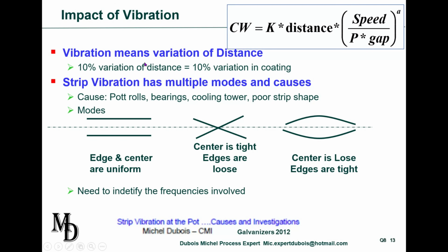Because vibration means variation of nozzle to strip distance. You immediately see that because they are proportional, a 10% variation of distance gives you a 10% variation of coating weight. When the distance is only 10 millimeters, a variation of 1 millimeter means 10%. But there are really many types of vibration, with different causes.